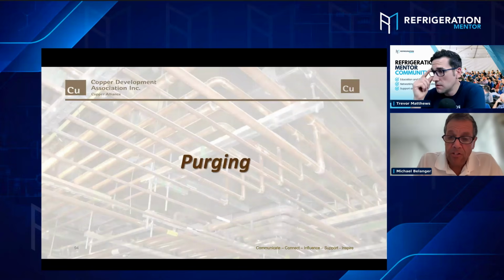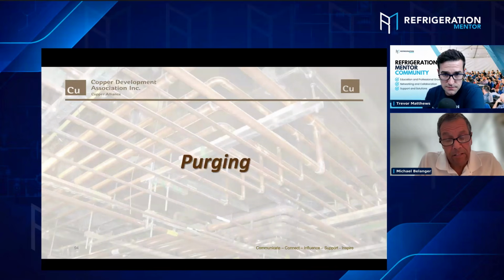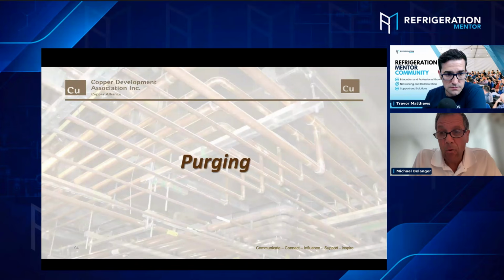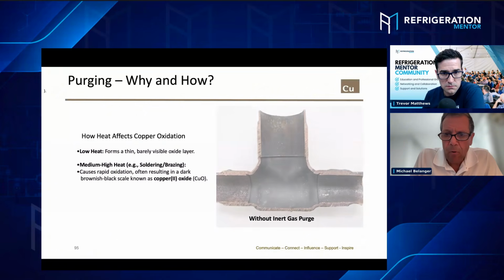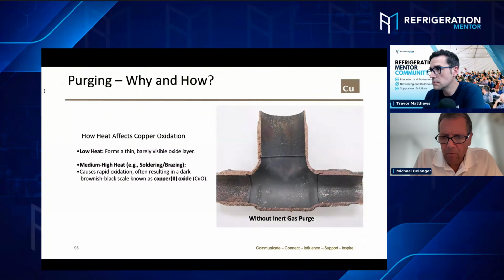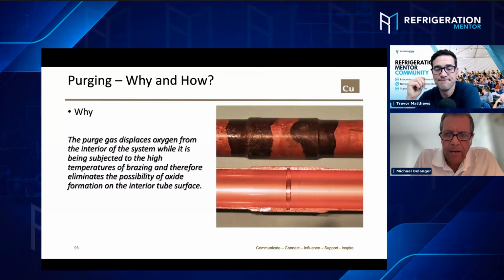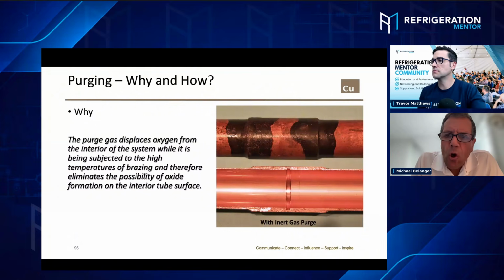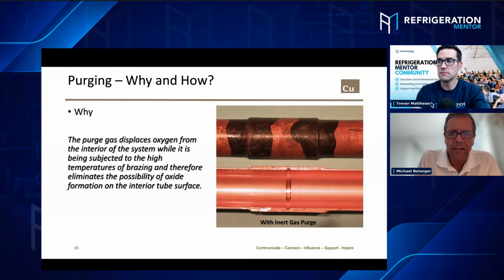I'm going to go through purging because it's really important. And frankly, we run into many instances where we get called because purging hasn't been done properly. So I'm going to go through it real quick. If you look at the fitting on the right without the inert gas purge, that's the oxidation. That is not good. That residue is not good. Again, in the photo on the right, if you look at the bottom tube, nice job with the purge. The top tube, there's no way you can tell if that's been purged properly or not. It's just physically impossible. It has to be done with an oxygen analyzer. I'll show you what that is.